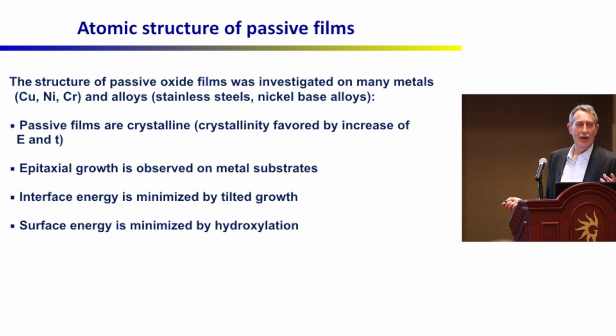Passive films are crystalline. There may be exceptions, but most of them, I would say, are crystalline. There is an epitaxial growth on the metal substrate. So you cannot understand the behavior of the passive layer if you don't know the effect of the surface structure. Usually the passive films will naturally minimize the interface energy, and nature is made in such a way that the way they grow will minimize the interface energy, and it will also minimize the surface energy.